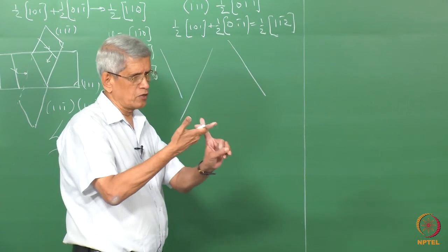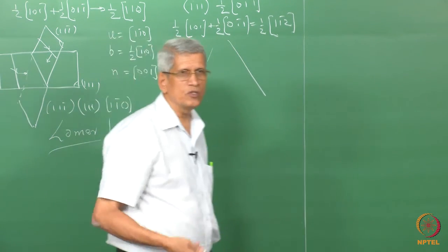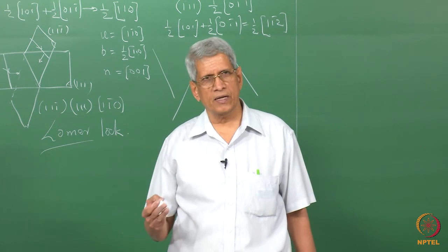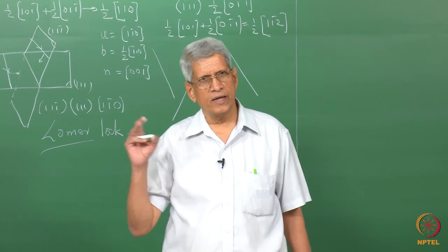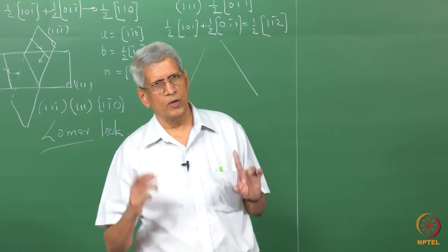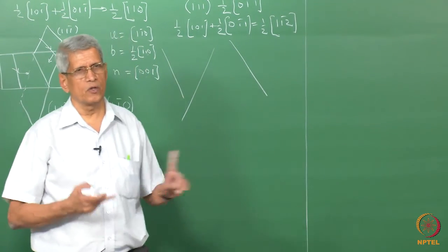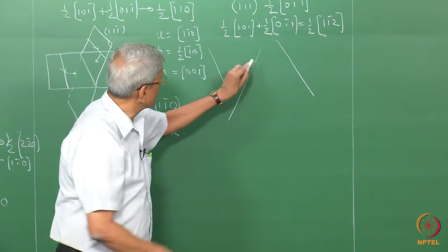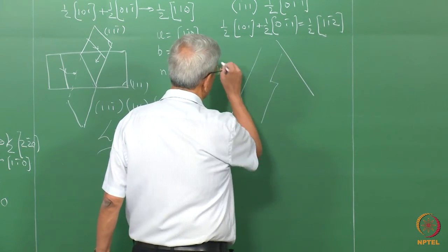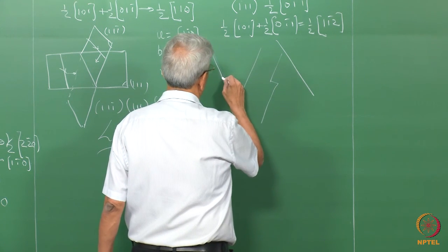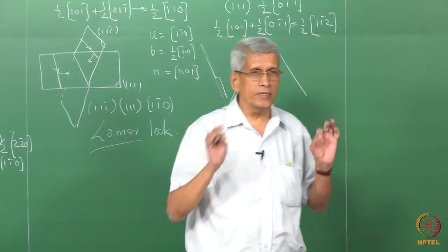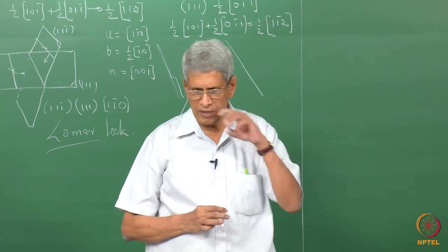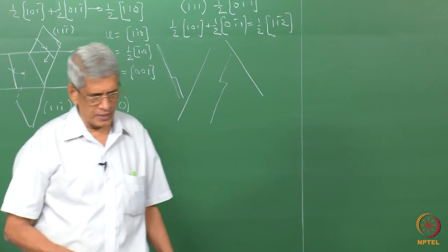One dislocation is there, another dislocation comes through it and cuts through it. When it cuts through, a small step will be generated in most of these cases. These steps are called either kinks or jogs, which we will talk about later. But for the present, we should understand that the dislocations will never interact, but when we apply a force, they try to cut through, and when it comes out, the dislocation might have a small step generated like this. By this process, the length of the dislocation has also increased. This is one way in which the length of the dislocation increases in the material.